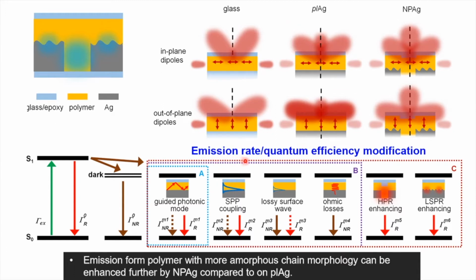And finally, we also found emission rate or quantum efficiency modifications that were due to the Purcell effect, where we're coupling the emission dipole to the resonance of the pore, and that's creating a change in transition rate and boosting efficiency in certain cases.